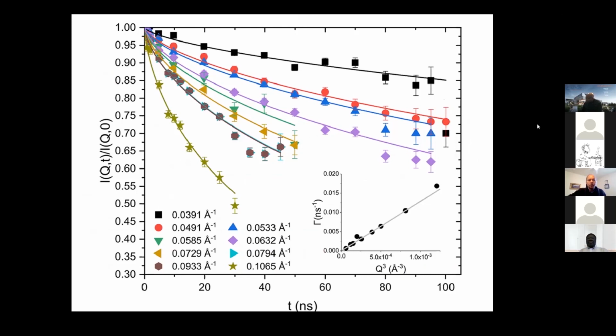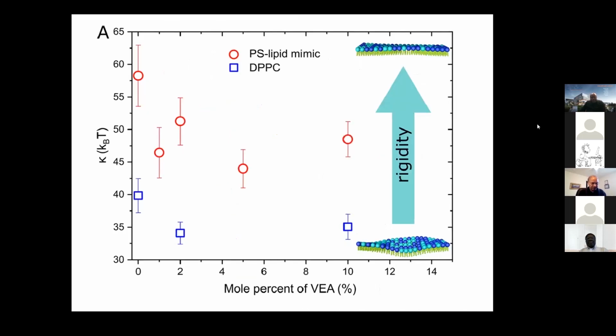So this is the actual data of the experiment. They all look like decay curves because the correlation just decreases over time. But the important part is how this is modeled. These are modeled as stretched exponentials, which is the model used for a thin sheet undergoing membrane fluctuations, which means from the curve fits, we can extract the bending modulus of the membrane. So we can access that information that we so dearly wanted, to determine the impact on the mechanical structure and function of these membranes based on the addition of vitamin E acetate. And that's what this plot shows.